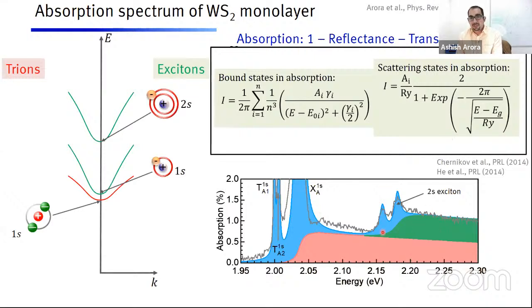So we model this spectrum by standard bound states and scattering states formula. And we find that we can fit this spectrum nicely by these step functions as well as these Lorentzians. So these two, of course, we discussed. These are the ground state trions, shown on the left side. This is the ground state of the exciton here. And then there is an excited state of the exciton, which was also well known from prior work, that the excited states of excitons are visible in these materials, such as the 2s state of the exciton.